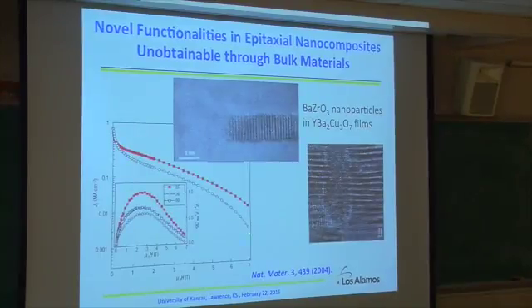For example, here the open circle is the current density versus magnetic field. Without nanoparticles, you see, especially at high field, the current drops a lot. But with nanoparticles, keep in mind this is a log scale, you really enhance the current capability a lot. Actually, currently this approach is licensed by industry. It's almost a standard technology; people right now are working on coated conductors. This is a very, very powerful technique if you can control it. If you can control it, that's your design.